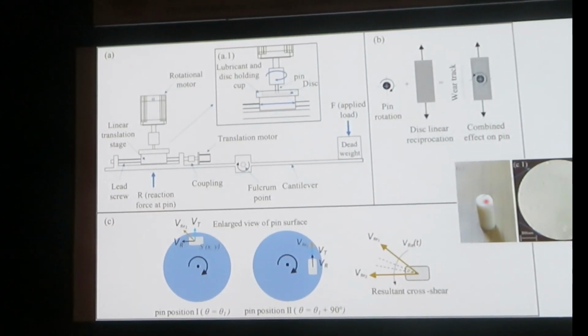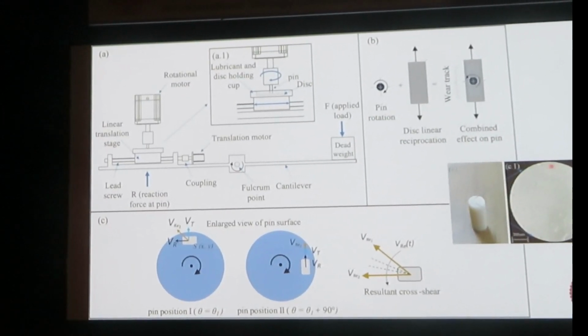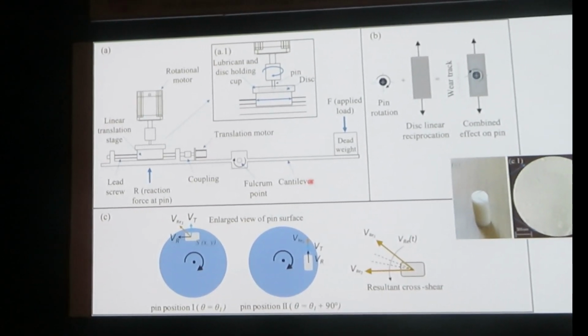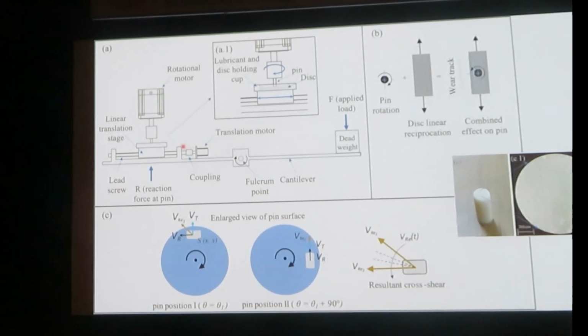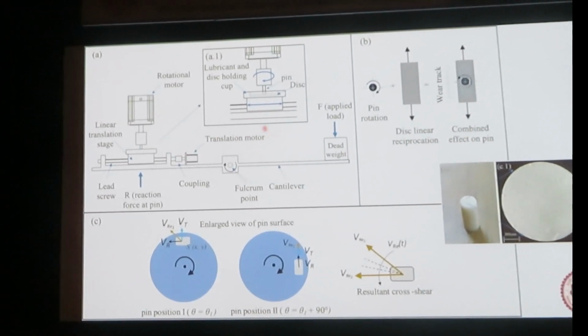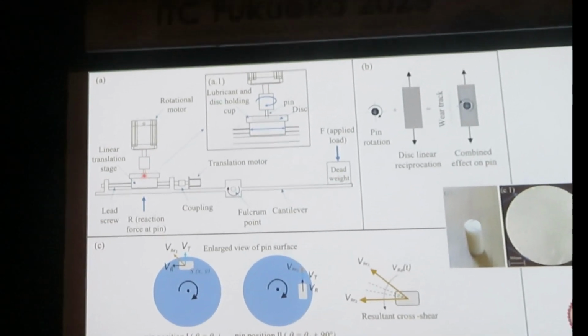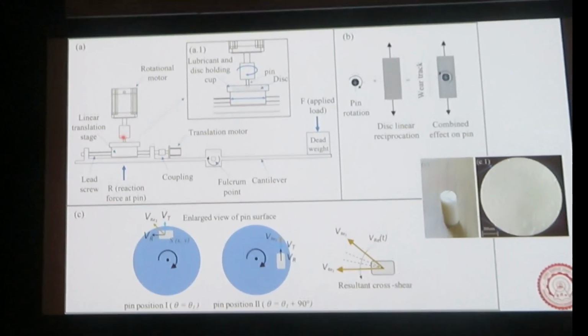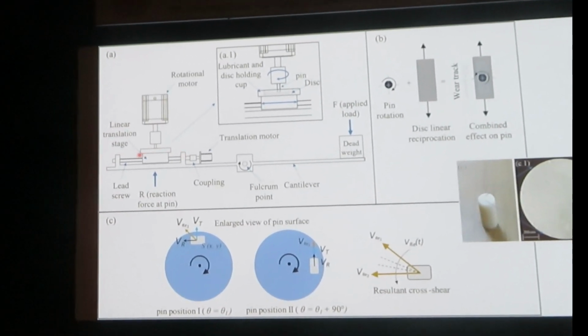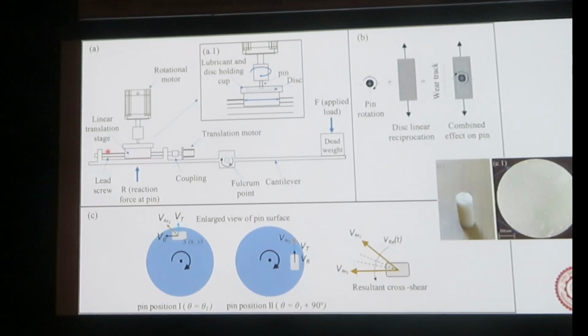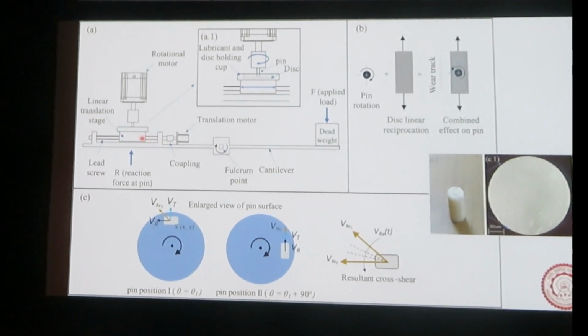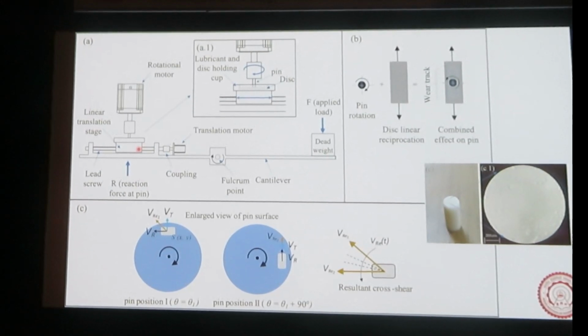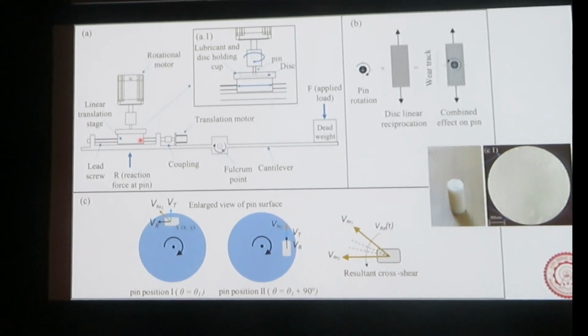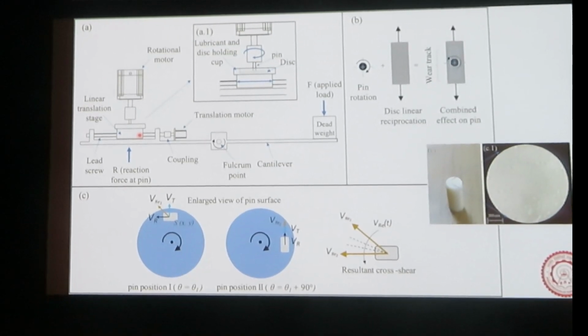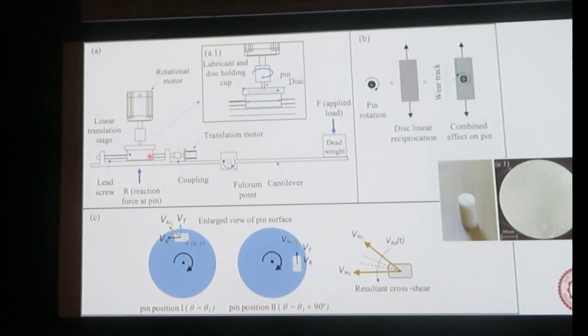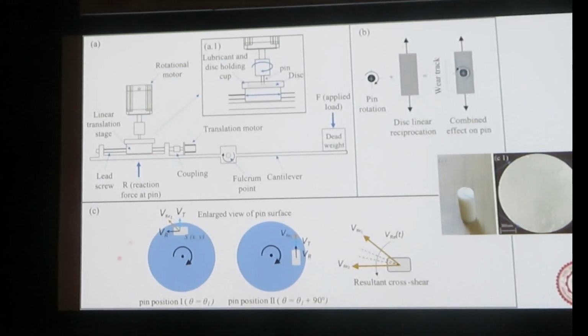And this is the sample after preparing, and this shows the surface. In this test, we have done again a multi-directional test, but on another machine which we developed. In this case, there is a pin. The pin is the polymeric part, and the pin is rotating on its own axis, and the disc, which is the counterface, is translating. So there is a translation and there is a rotation. That gives us a cross shear motion of about 270 degrees, which means the wear tracks are always crossing each other. And this explains how it all works.